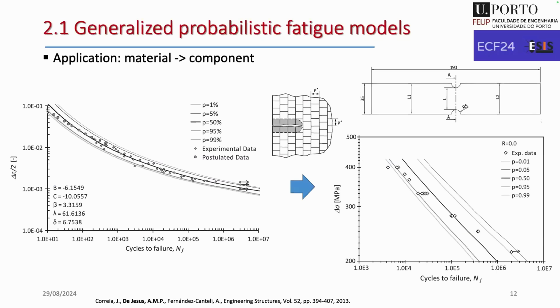Afterwards, we were applying this fatigue S-N field, but it could be different parameters on the y-axis. We were exploring this to, for example, model the fatigue behavior of notched components, assuming that the fatigue life will be a propagation of a crack, and that crack propagation is a result of successive crack reinitializations across a crack path. So starting with the material model, we were able to predict the fatigue S-N field for the notched component.